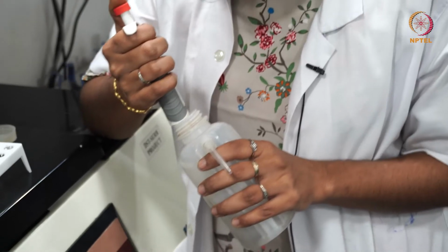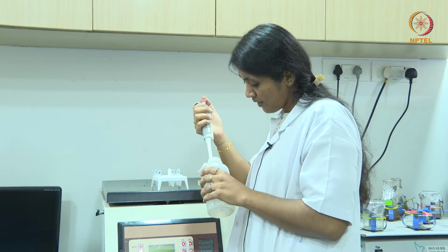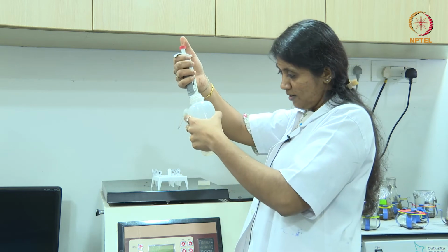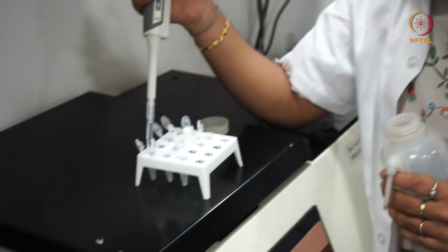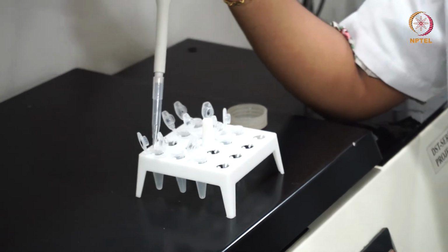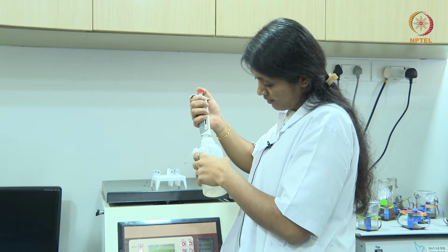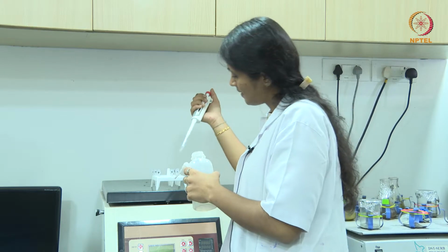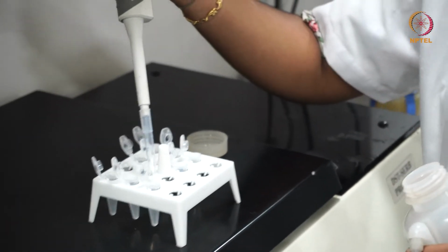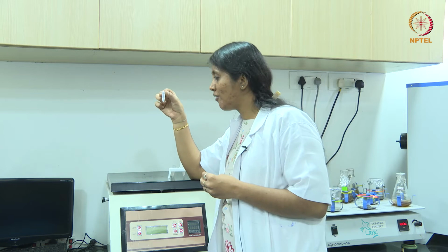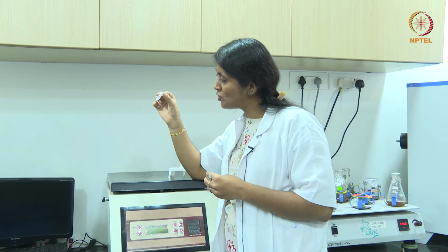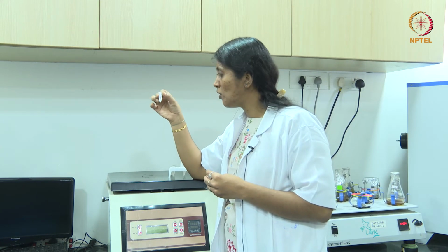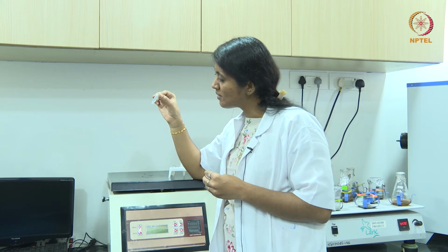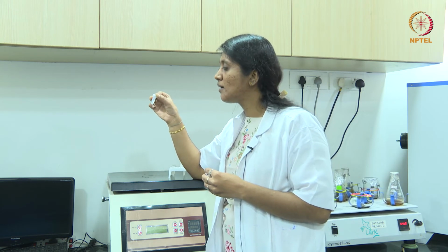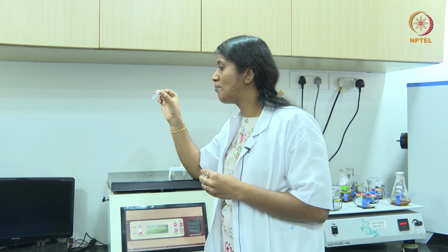For the positive control, I am taking 950 μL of DD water. This DD water completely ruptures the RBCs. So we take these ruptured RBCs as the positive control. Now I weighed bioactive glasses, 10 mg of sample, in 950 μL of PBS. I'm going to sonicate this for complete dispersion of particles.